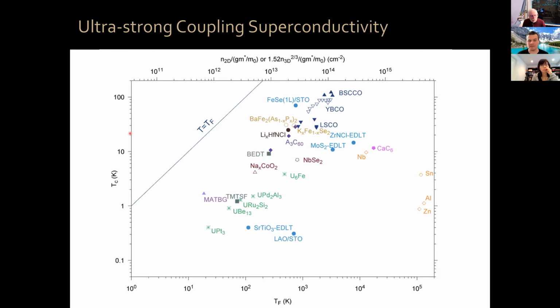In fact, usually we characterize how strongly coupled superconductors are by looking at a log-log plot of TC over TF. Conventional superconductors tend to be around this region. For example, aluminum, which has a 1 Kelvin TC, and a Fermi temperature, which is the same as density normalized by various factors here, so that you can compare 2D and 3D superconductors.